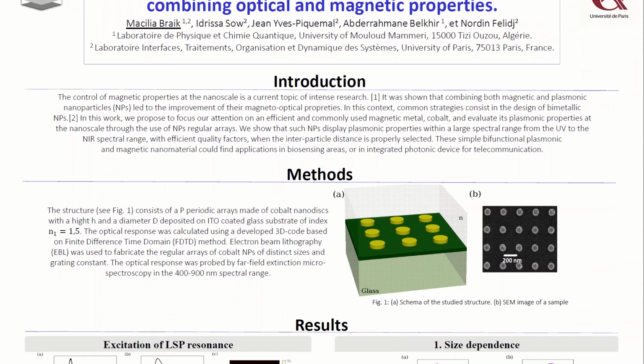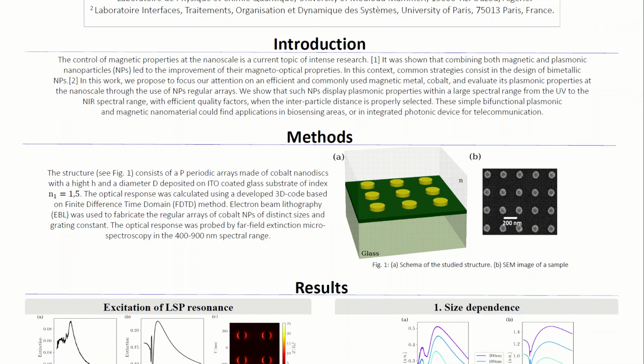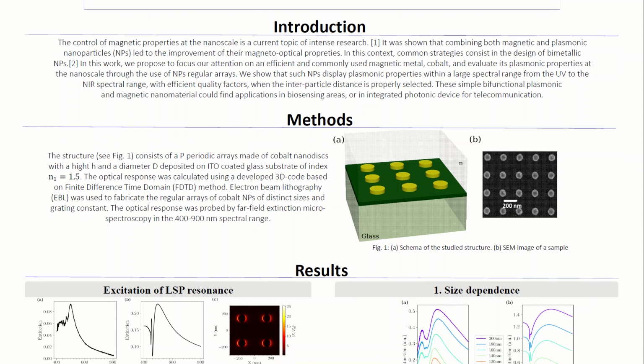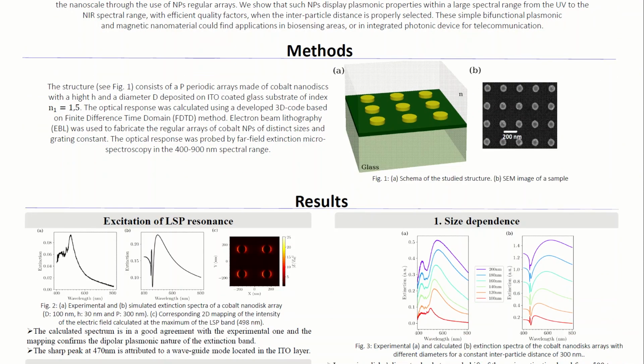So we chose a structure that consists of periodic arrays of cobalt nanodisks deposited on an ITO-covered glass substrate. The structure is fabricated by electron beam lithography and probed with optical spectroscopy. The experiments are supported by FDTD calculations using a home-developed code.